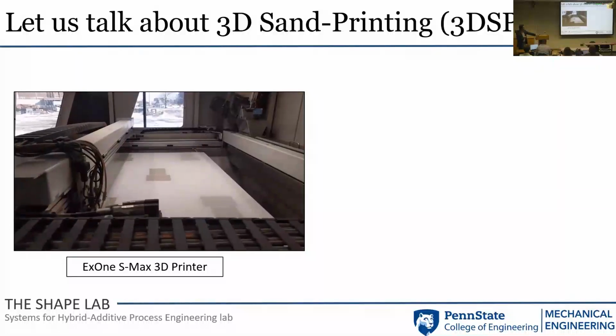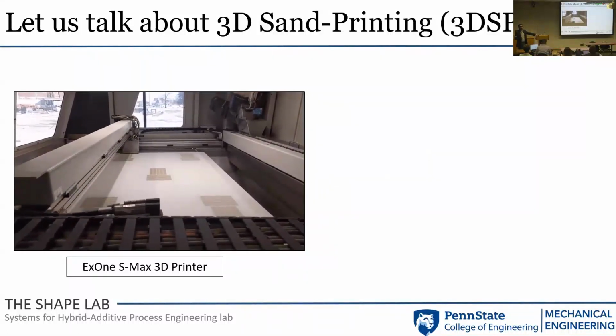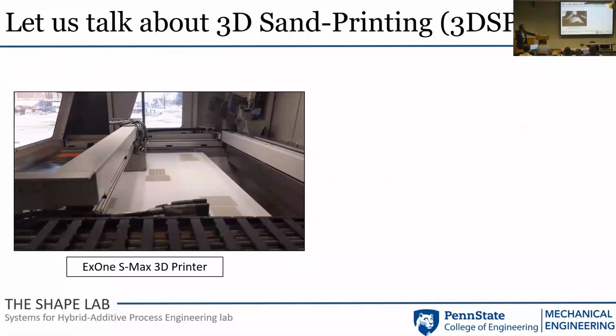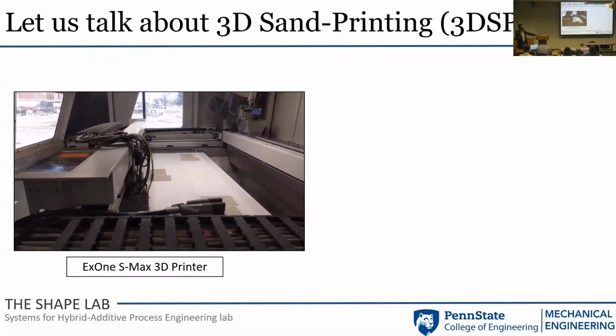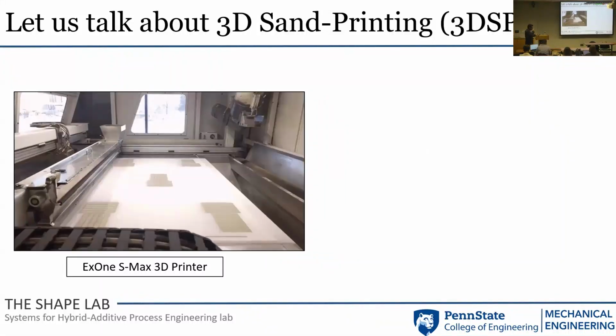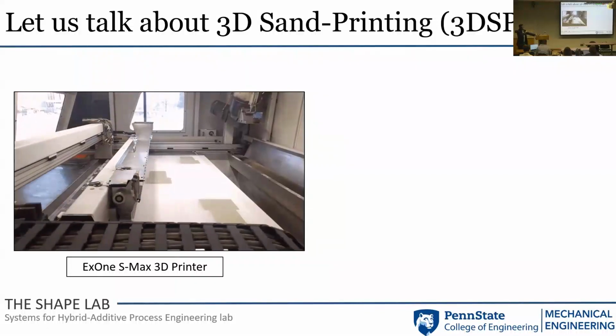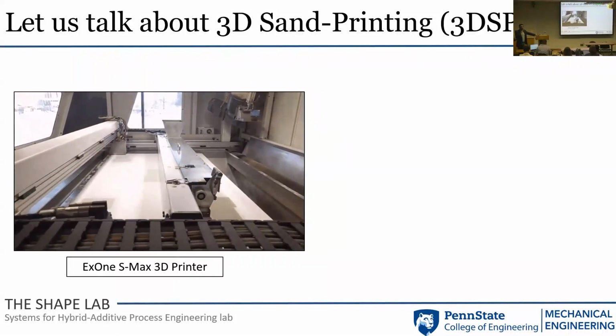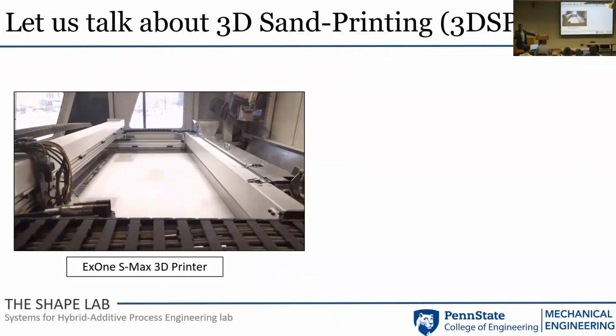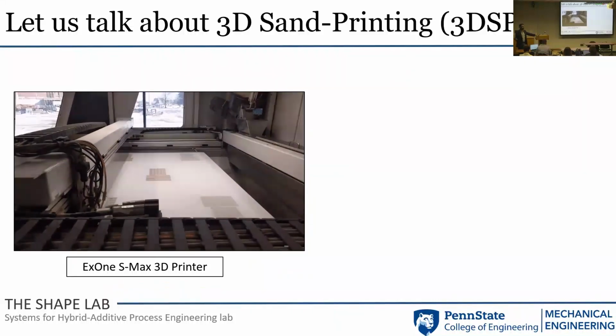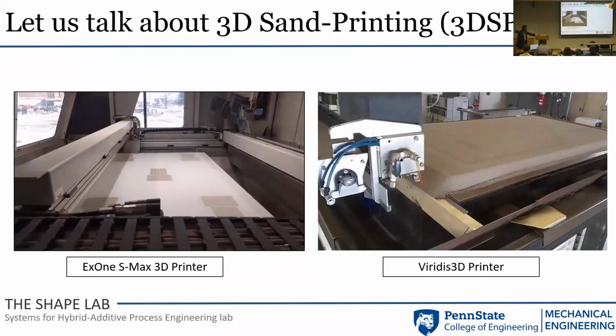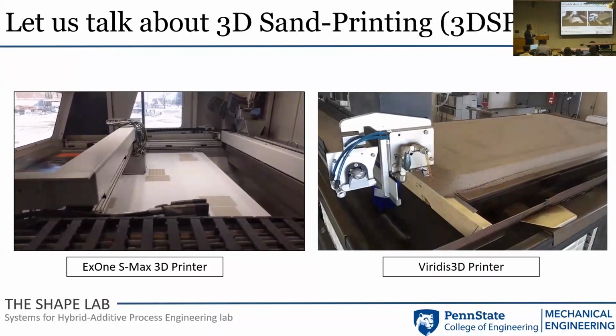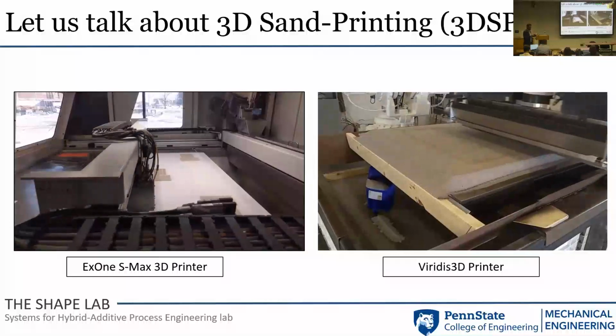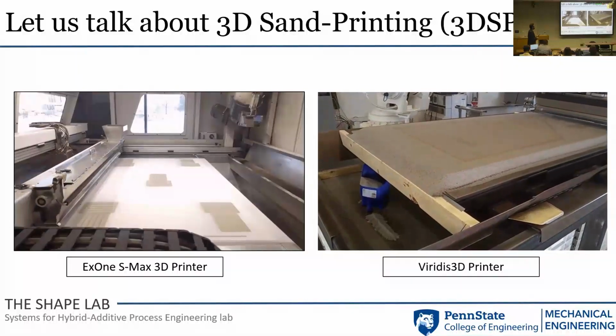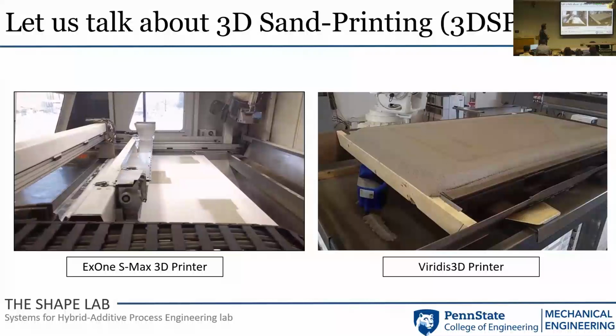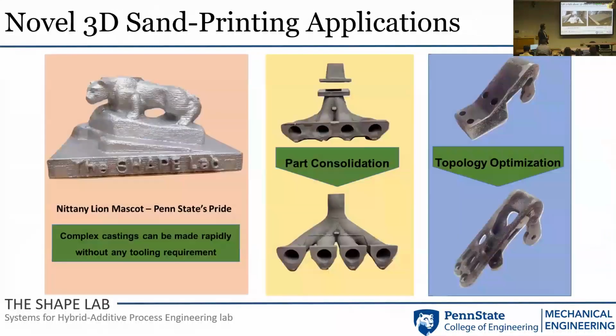So the way it works is you spread a layer of sand, which is traditionally used foundry silica sand, and you can put down binders. There are different types of binders. Furan is a commonly used one. So the good news is, if you are a casting or a foundry company, you are not introducing new material, new organic compounds that you are not already using. That removes one barrier. There are different OEMs that are available, but again, we want to solve problems that are not tied to one particular OEM. Like for example, in this one, you're not spreading the entire layer of sand and you're just depositing for whatever mold you need.